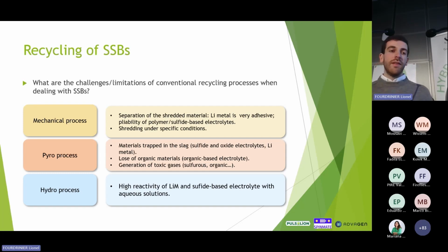Then for the separation after the mechanical process, as I explained before, in current lithium-ion batteries, you can separate the different fractions after the shredding with some physical separation. But in this case, the lithium metal is very adhesive, so you might need some chemical separation apart from the physical separation. That's something we will see later. And then regarding the pyrometallurgical process, the main problem of this process with the solid-state batteries is that some materials will get trapped in the slag, like the sulfide and oxide electrolytes, and also the lithium metal, and it would be very difficult to recover this from the slag.